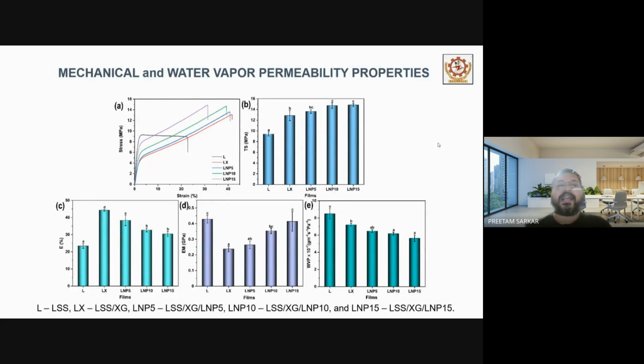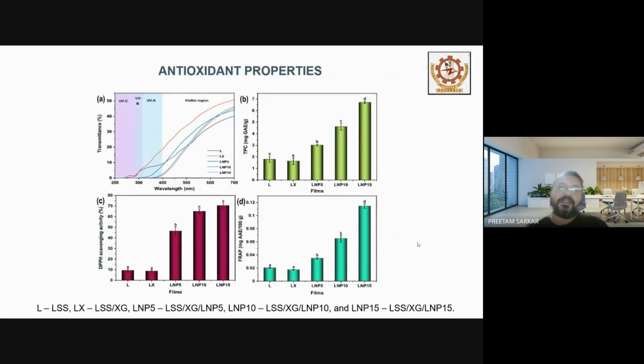And these are our mechanical properties. When you talk about packaging material, the mechanical properties become very important. We calculate something called tensile strength. As we increase our nanoparticle concentration, tensile strength increases. We can also see the water vapor barrier property, the permeability, reduces, and that means it's a good film with the increase in LNPs. The target of our work was to prepare these films using lignin nanoparticles to improve the antioxidant activities. So this work is focusing completely on antioxidant activity.